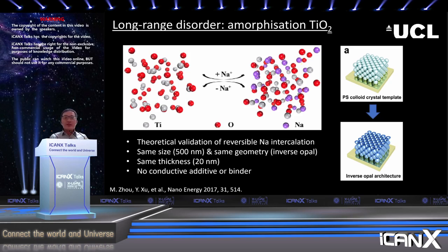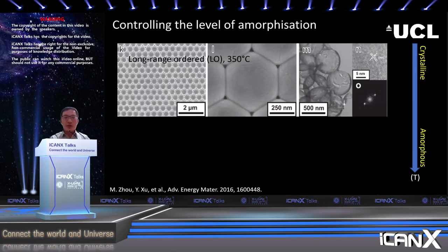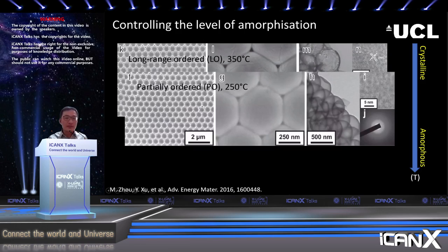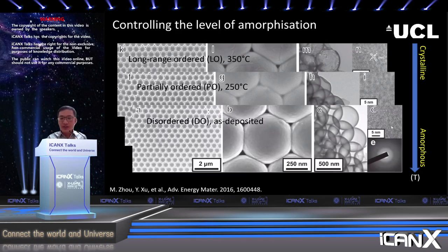We use different post-annealing temperatures to control the level of amorphization of titanium dioxide. That's also the beauty of this synthesis, which is very simple to follow and can be done by anyone who has the ALD facility. So if we increase the anneal temperature to 350 degrees, we are able to obtain crystallized titanium dioxide. And by lowering the anneal temperature to 250 degrees, we obtain the material that has a mediocre crystallinity. But if we didn't anneal the material at all, then the as-deposited titanium dioxide actually shows an amorphous structure.